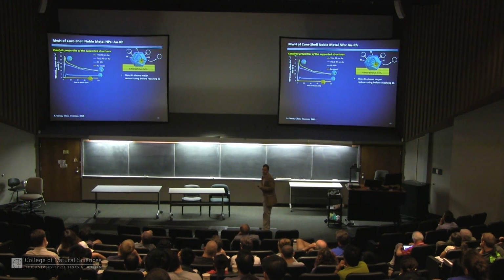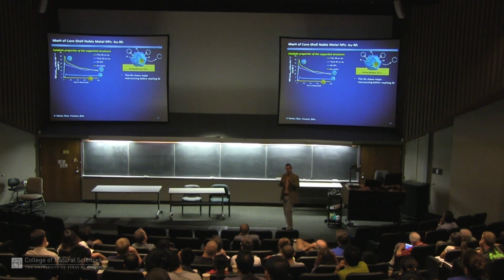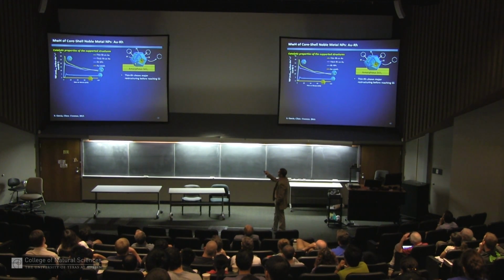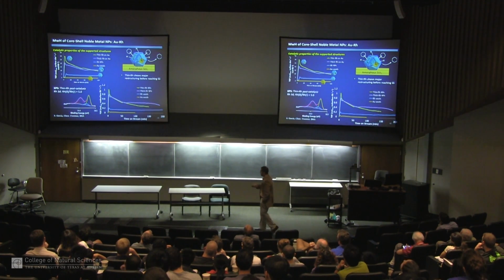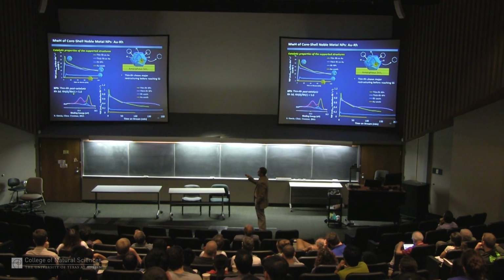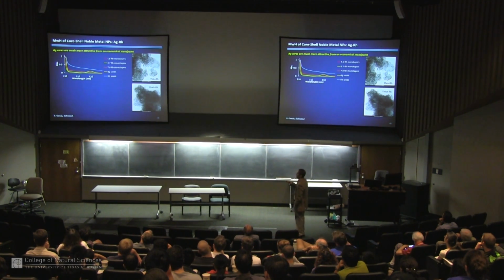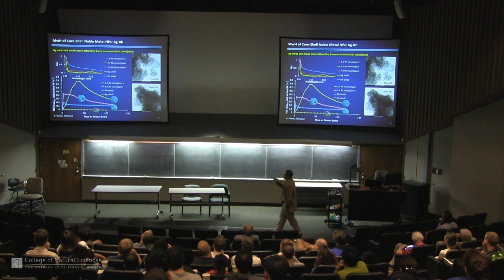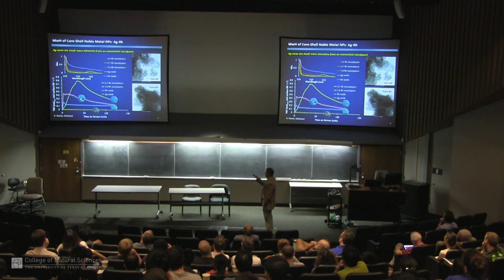They take longer to reach steady state, and that's because there's some rearrangements going on, and the shells are a little bit strained. This is a cartoon of what you can think is going on here, and the silica is just the support. And we know for a fact, from measurements like XPS, there is also a difference in the oxidation states at the surface when you have an electron-rich and electron-donating core, such as gold in this case. We did the same for silver, and this is work that Stephanie Garcia, who's now working for a nanotech company in Houston, worked on. And you can see that, again, if you have these core shells, they're much more active.